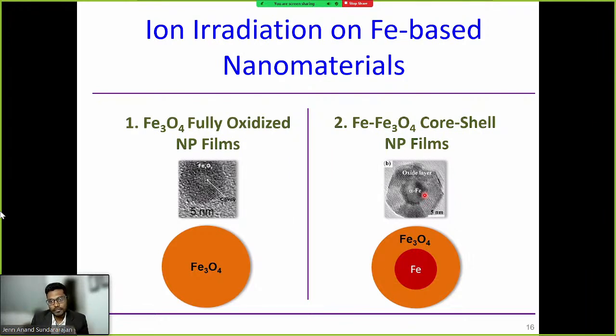One thing you can see right off the bat is that it has more grain boundaries. You can see from this picture, these are grains, you can see how atoms are aligned in one plane, and there is an interface as well. But when you look at the fully oxidized nanoparticle films, it's either single crystal or multi-crystal, but there are very few grain boundaries and pretty much no interface. So let's keep that thought in the back of the mind.